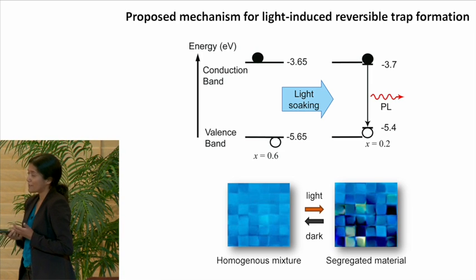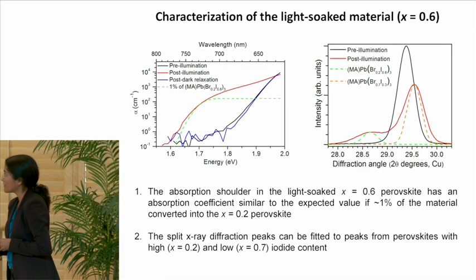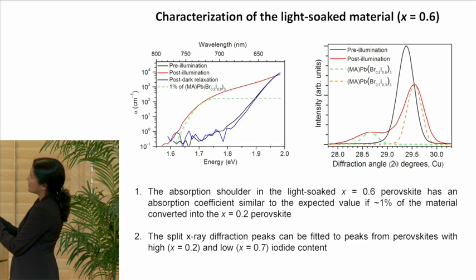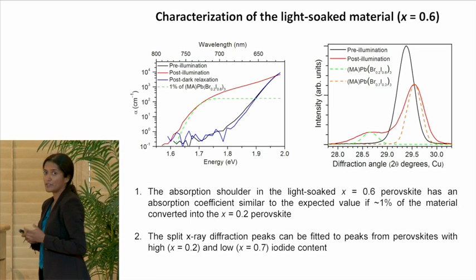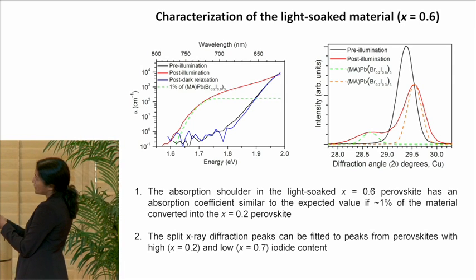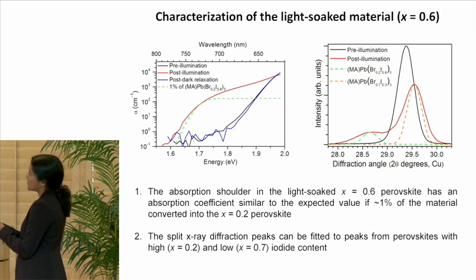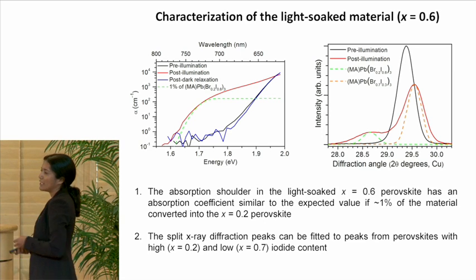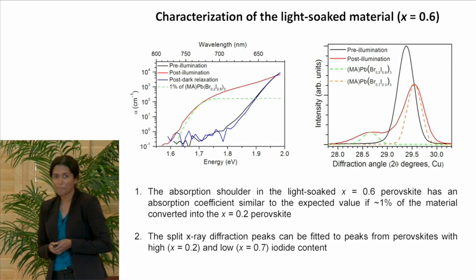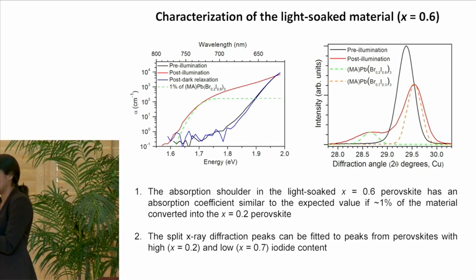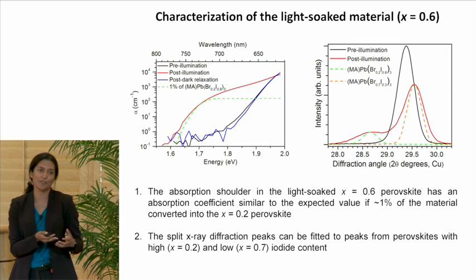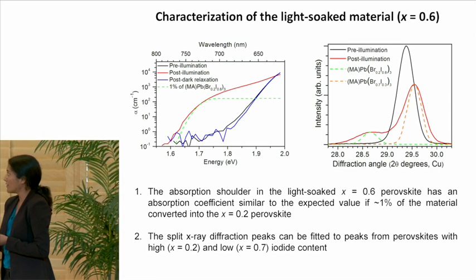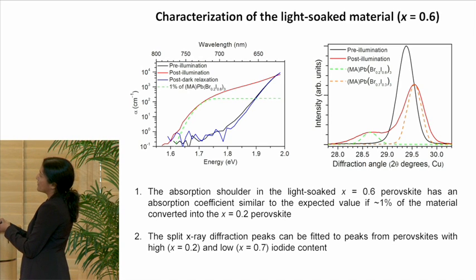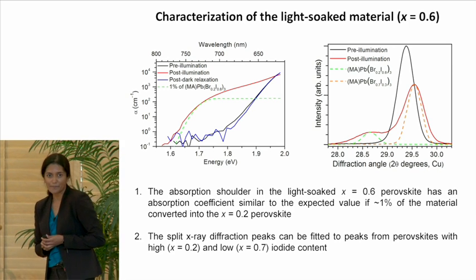And our data so far support this speculation. If we were to fit this shoulder that we see emerge in the light-soaked material, that actually corresponds quite well to what we would expect from the absorption spectrum of the x equals 0.2 material if about 1% of that material converted. And if we were to form regions of high iodide content, that means we must, by necessity, form regions of low iodide content as well. And that also explains the split diffraction peaks, because here, this peak matches well with the x equals 0.2 material, and this peak matches quite well with the x equals 0.7 material.